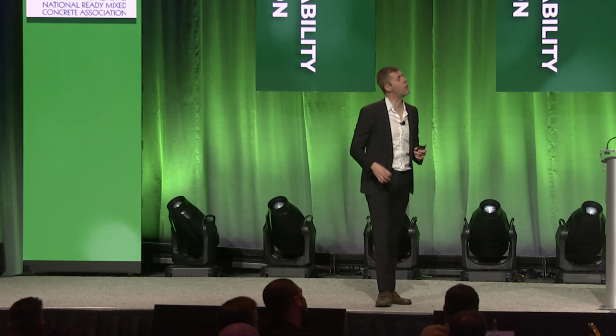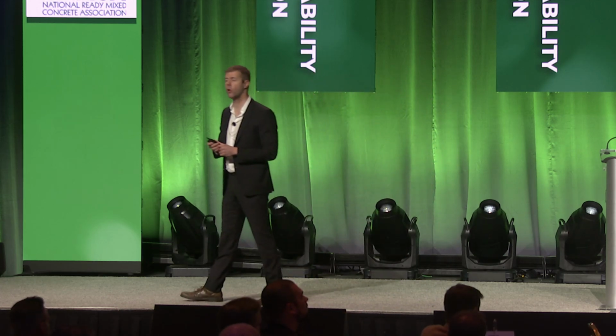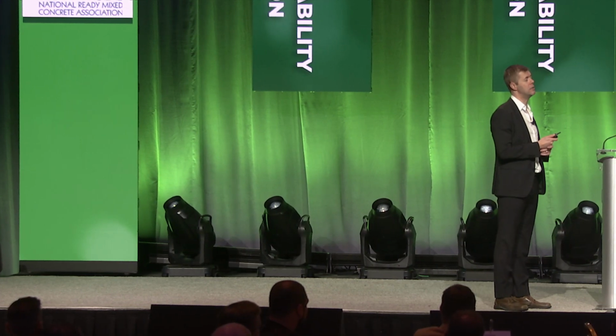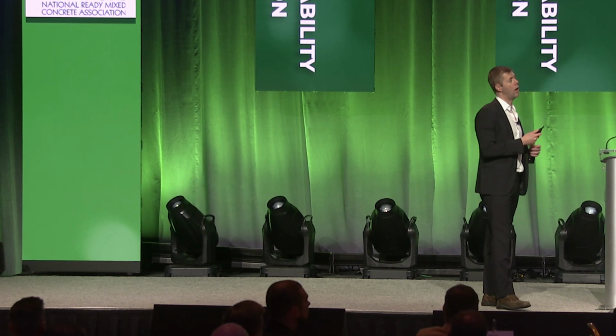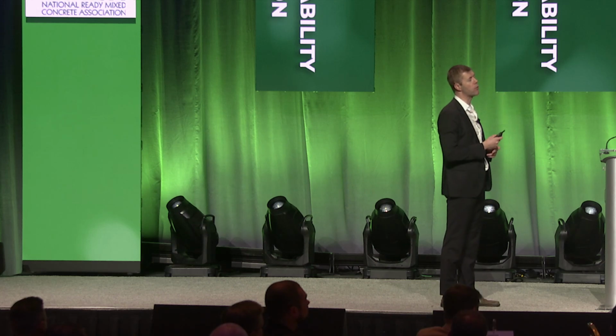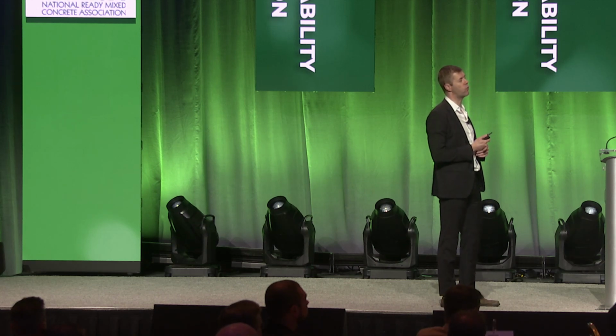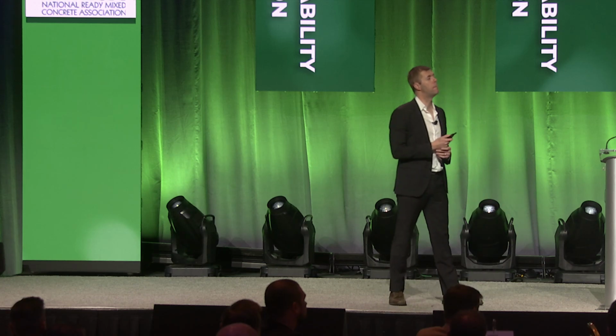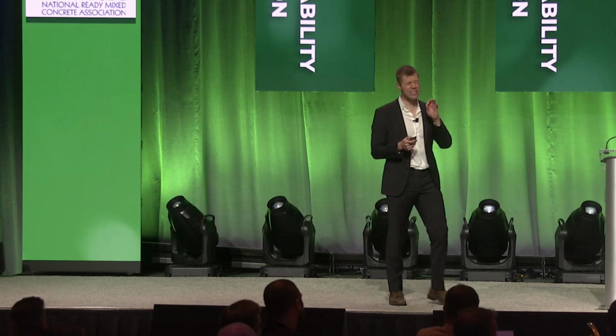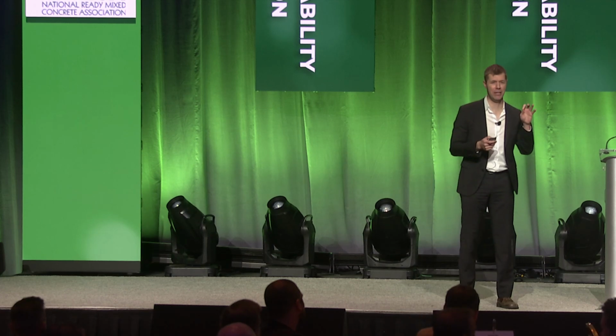And let's everyone look on the far right. See that number, 0.47, 0.42? Both of them met the specification. There was nothing wrong with either one of the concretes. They just happened to pick a number, 7 inches. Because the water reducer that we were using was a little bit higher dose than it should have been, slump was higher than it needed to be. And they should have dropped the water reducer. Instead they dropped the water. They went from a 0.47 to a 0.42. They were already within the spec, but the slump was still out. This is silly. This shouldn't happen.